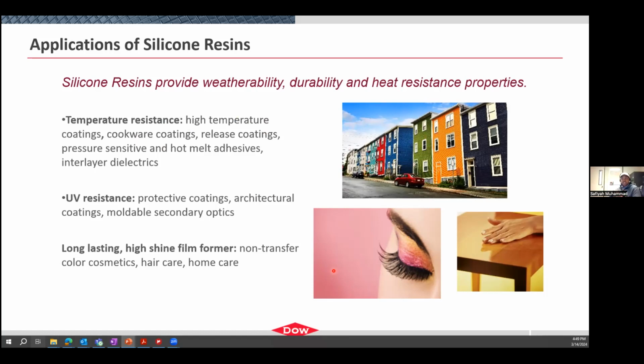Again, because that bond is so strong, it's often resistant to UV degradation. So we actually use this for architectural coatings as well. A lot of our silicone resins are used to paint bridges and paint buildings, painting things that have constant interaction with the sun and harsh environment because it will last longer than some traditional acrylic-based coatings, for example. And then in the last space, we have personal care and home care. So one thing that silicone resins allow is that it serves as a film former so that you don't transfer material from one space to another. So if you think about wearing a lipstick or wearing some eyeshadow, right? You don't want it to rub off or to transfer onto a different surface, right? So we take advantage of silicone resin properties to be a film former and to keep the contents within the area that you want it to be in.